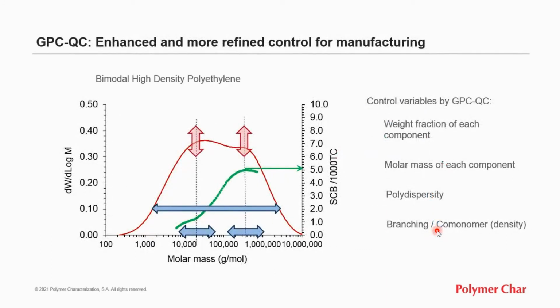So we can see here that several variables can be used for control of the production of this type of products. As I said, the weight fraction of each component may be changed, their molar mass, polydispersity, branching distribution, or comonomer content. Most of that information is not available when measuring only melt index and density. So we're sure that companies will benefit from implementing this technology in manufacturing. Some companies already are doing it, in order to reduce off-grade production and also contribute to smoother startups and transitions in reactors.